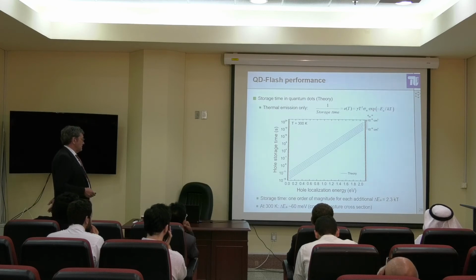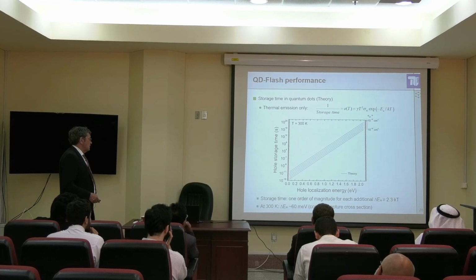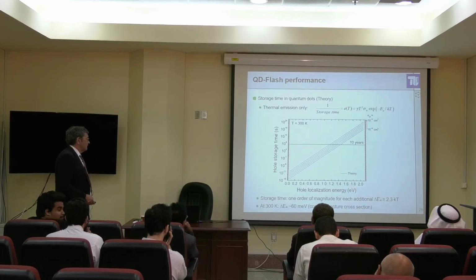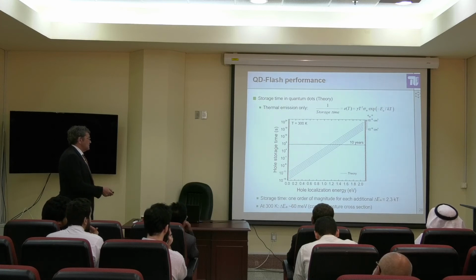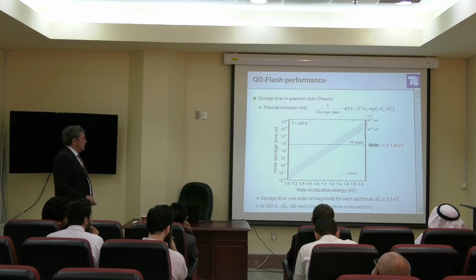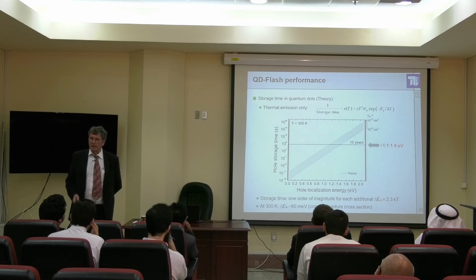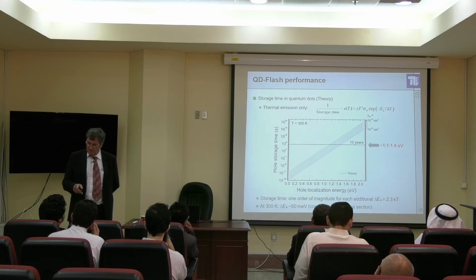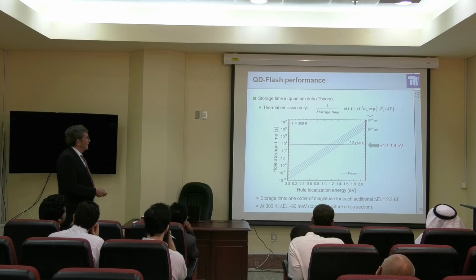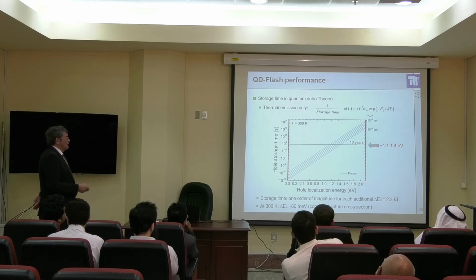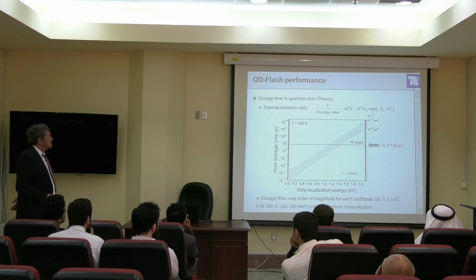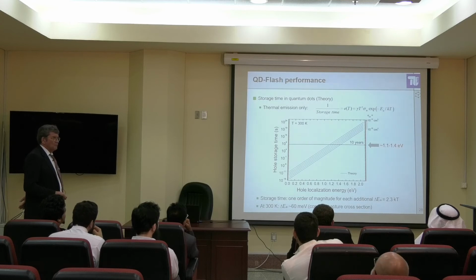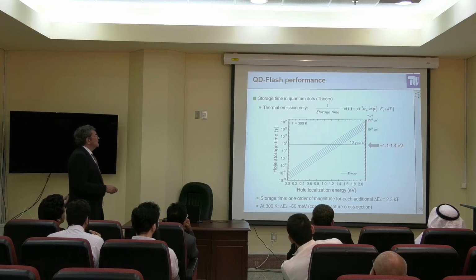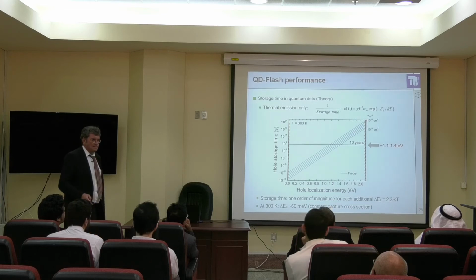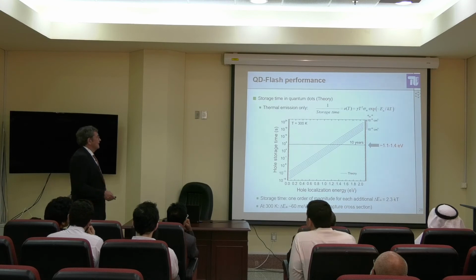At 300 Kelvin, you need a minimum ΔE_A of 60 milli-electron-volts, 2.3 times 26. And finally, if you want to have such a memory where the information is stored for 10 years, 10 years, like flash, you must end up at this line here, between 1.1 and 1.4 electron volts. But we do not know about this number here. That's difficult. That's the subject of the thesis of Elisa Sala to find out.